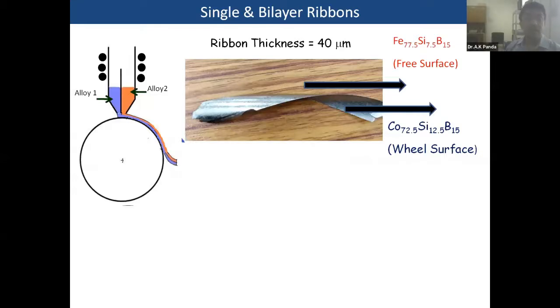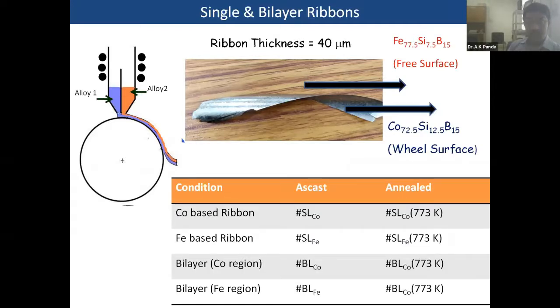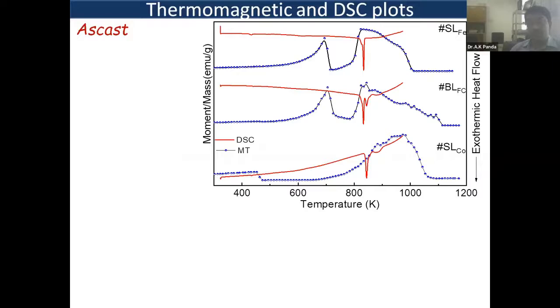Very interestingly, what you do is, in a crucible that contains two compartments, we take two alloys, alloy 1 and alloy 2, melt them using induction melting and eject them out on a copper wheel, and you get a bilayer ribbon with the top layer like iron silicon boron and the bottom layer like cobalt silicon boron. So it almost looks like a single ribbon, right? And then we term it SLCO for a single layer ribbon and SLFE for a single layer ribbon. Single layer ribbon means it is a ribbon that is only one alloy. And bilayer ribbon is the one where you take two alloys in the two compartments and you process it out, where the top layer is one alloy and the bottom layer is another alloy. Okay, so basically then I move to the next slide.